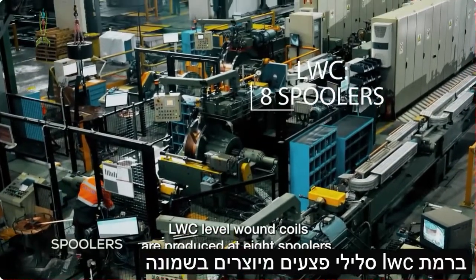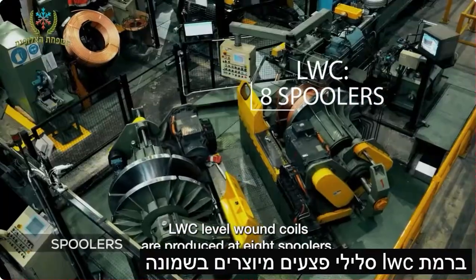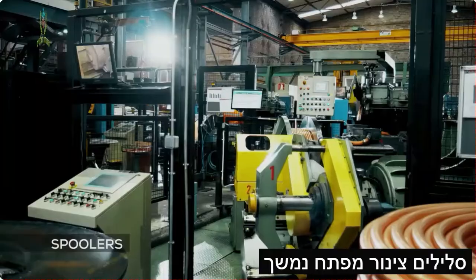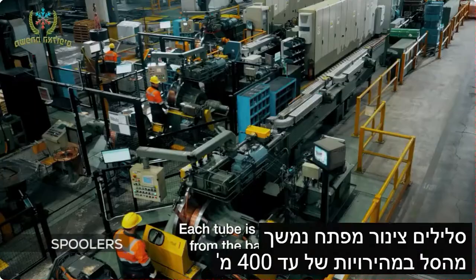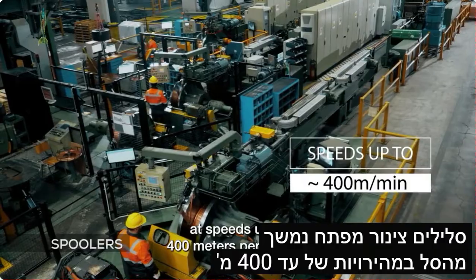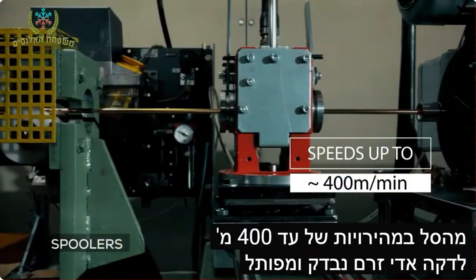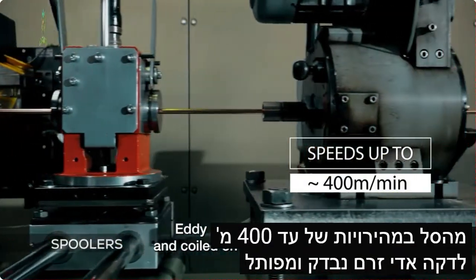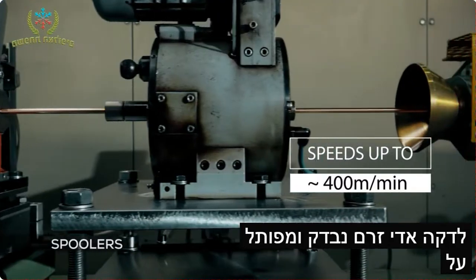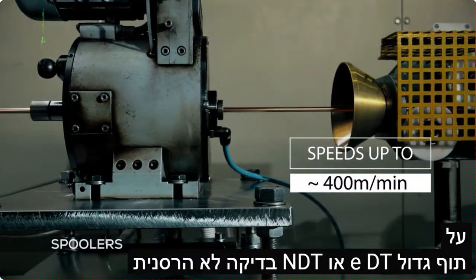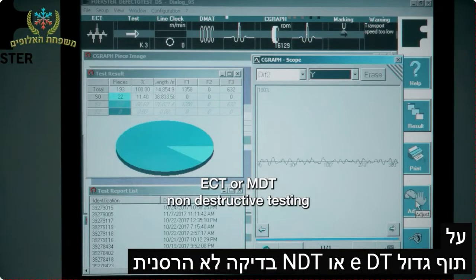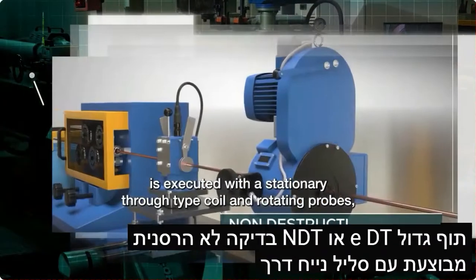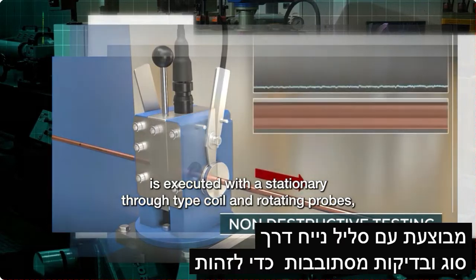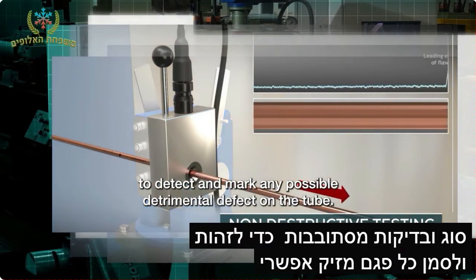LWC, level wound coils, are produced at 8 spoolers. The tube is drawn from the basket, at speeds up to 400 meters per minute, eddy current tested, and coiled on a large drum. ECT or NDT, non-destructive testing, is executed with a stationary, through-type coil and rotating probes, to detect and mark any possible detrimental defect on the tube.